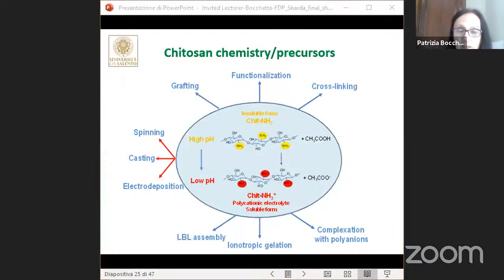So, as said before, chitosan undergoes a chemical equilibrium in slightly acidic solution and becomes insoluble at high pH. The capability of chitosan to turn from soluble to insoluble forms by changing pH is fundamental for the fabrication of composite chitosan structures with specific functionalities. Starting from this chemical behavior, many methods of fabrication have been proposed in literature. The most representative are solvent evaporation, cross-linking, layer-by-layer assembly, electrodeposition, and also ionotropic gelation.